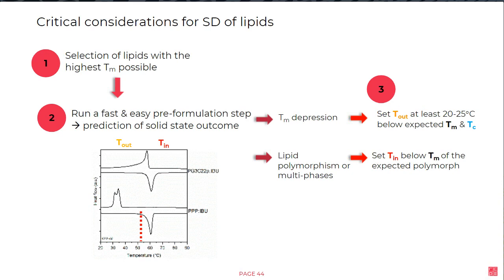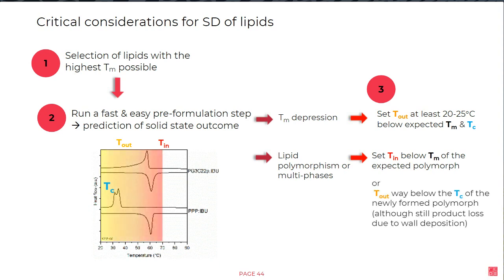If this is not possible, because dry modeling is not sufficient or simple particle attributes are not matching these conditions, then we need to fix the outlet way below the recrystallization at least (20 to 25 degrees) in order to improve a little bit the processability of such lipids.